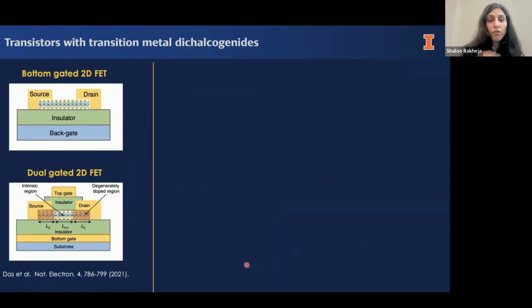There are two flavors of these devices that people have been talking about. The first one is a back-gated 2D FET. As you can see, we've applied gate voltage to the backside of the device. And the second one is a dual-gated transistor where you have a top gate and a bottom gate. The nice thing about this bottom device is that the layout minimizes the overlap capacitances between the source and the gate and the drain and the gate. So it's very exciting. And the other thing is we can degenerately dope the regions underneath the source and drain to get really nice ohmic contacts.